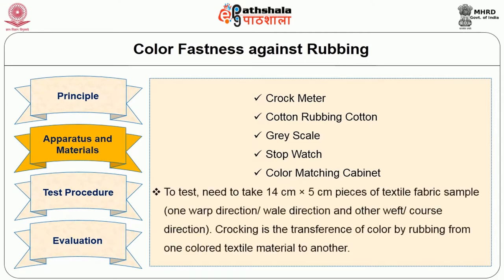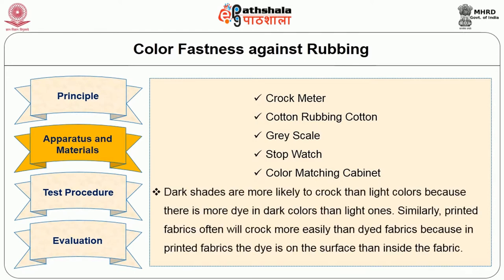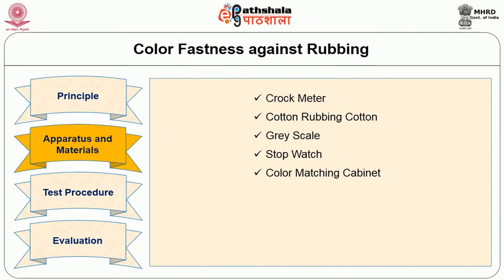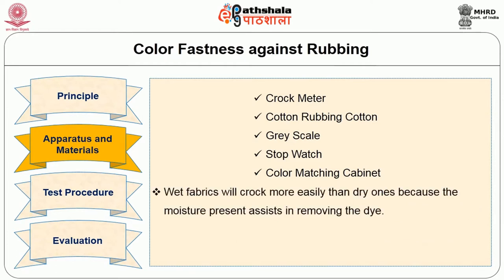The sample dimension used in this test method is 14 cm by 5 cm, one in the warp direction and another in the weft direction in the case of woven fabric. Crocking is the transference of color by rubbing from one colored textile material to another. Dark shades are more likely to crock than light shades because there is more dye in the dark colors than in the light ones. The crockmeter is also suitable for printed woven fabrics. Dyed fabrics are less susceptible than printed fabrics because the dye is inside the fabric rather than on the surface. Wet fabrics will crock more easily than dry ones because the moisture present assists in removing the dyes.